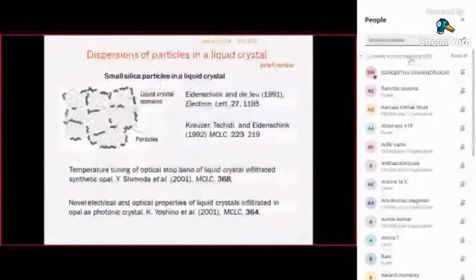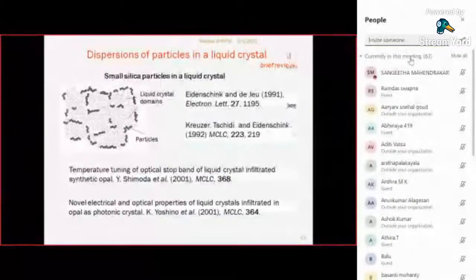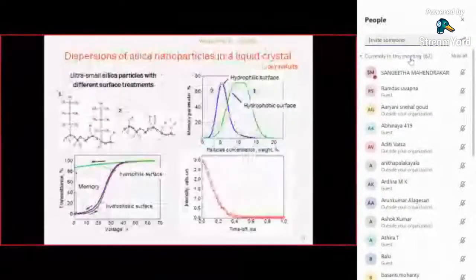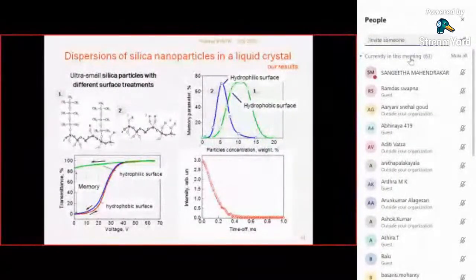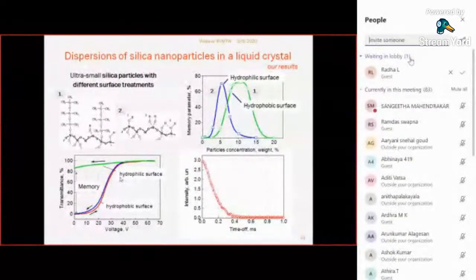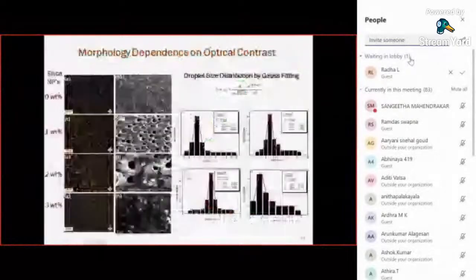For that, we did the capping of some nanoparticles before the doping. So if we cap the nanoparticle with a proper hydrophilic or hydrophobic structure like this one, we get a better response because there is no segregation in the liquid crystal matrix, and we get an improved transmittance in that case. So I am showing a result of my own paper.